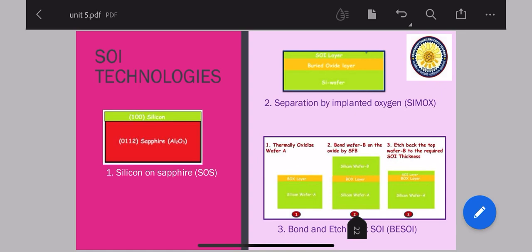According to the material selected for the insulator, we categorize SOI into basically three types. First is Silicon on Sapphire (SOS): we take sapphire material and on that we deposit silicon — here you can see 100 silicon refers to the orientation of the silicon. The second one is SIMOX, Separation by Implanted Oxygen, which uses a buried oxide layer with silicon on top and the SOI layer on top of that.